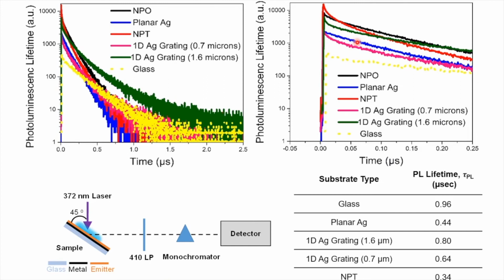That's expected because you will get some increase in the non-radiative recombination anytime you put an emitter near a metal, especially within 5 nanometers of the metal. However, further out, we can get enhancements or reductions in the emission quantum efficiency, and that will affect the lifetime. Compared to planar silver, you can see that the most enhancement in intensity and shortening of the lifetime occurs for the nanoparticle silver. So that's consistent with the idea that that's also enhancing the stability the most by that mechanism that we proposed, where we're using an increase in the spontaneous emission rate caused by the Purcell effect.